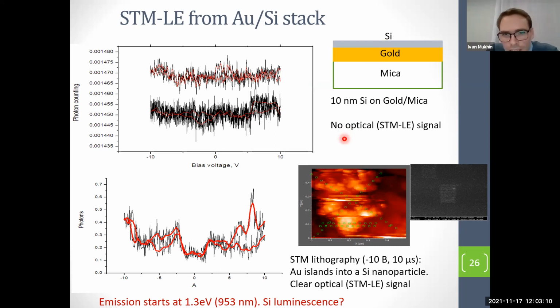Like it's shown here, it's a hybrid metal-dielectric plasmonic nanoantenna, a silicon-gold nanoantenna, and you can produce it in the shape of a ray. You can produce a single structure, and this one gives an optical signal. So we applied bias voltage and collected the optical signal, and you can clearly see that we have optical signal in that situation. More importantly, the emission starts not from 1.8 electron volts, like it was for gold material, but from 1.3 electron volts.